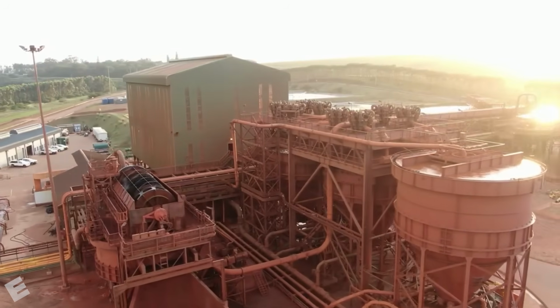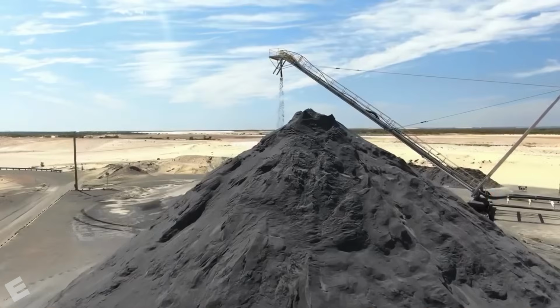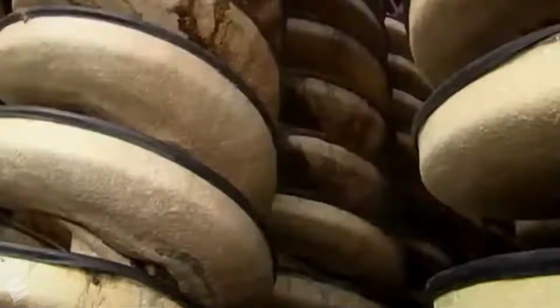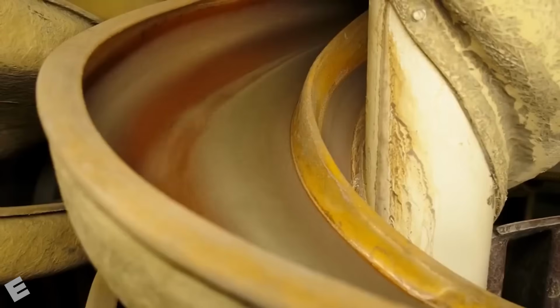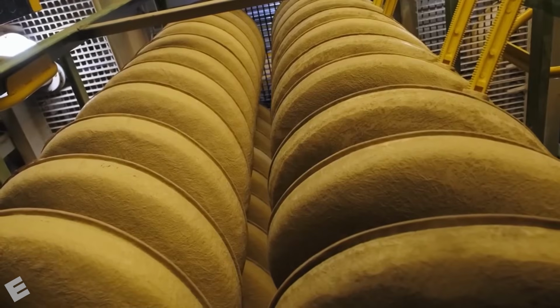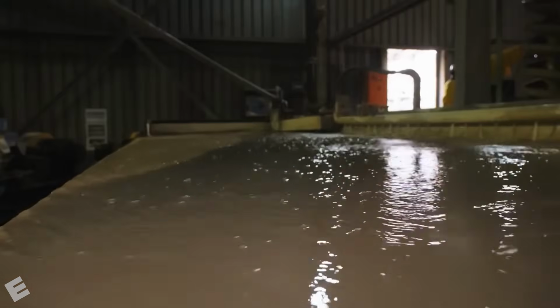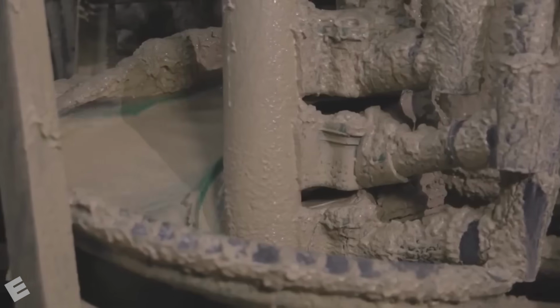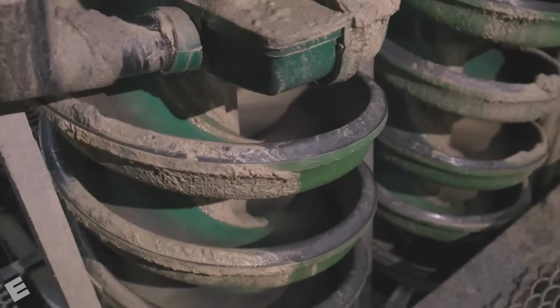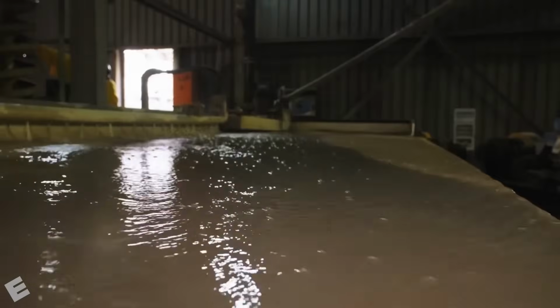When the slurry reaches the processing plant, it is fed into a series of gravity spirals. These cleverly designed machines operate somewhat like the pans once used by gold prospectors. As the mixture flows downward through the spirals, gravity, water flow, and motion begin separating the different materials. The heavier minerals containing titanium move toward the inside of each spiral. The lighter grains of ordinary sand move toward the outside, where they are removed. The result is a dark, heavy mineral concentrate containing a much higher proportion of titanium-bearing material.